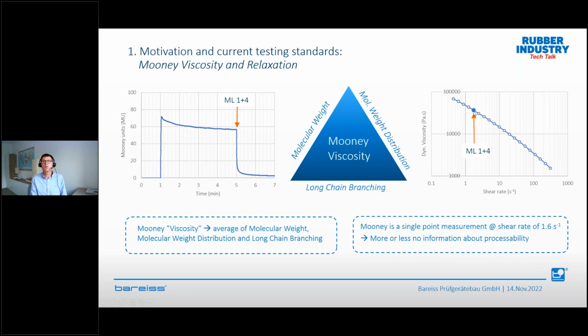So you measure only at one shear rate, but what happens in your processing on an extruder, injection molding machine, mixing line, you always have lower shear rates and you also have higher shear rates. But you get no information from a Mooney what happens at these lower and higher shear rates.